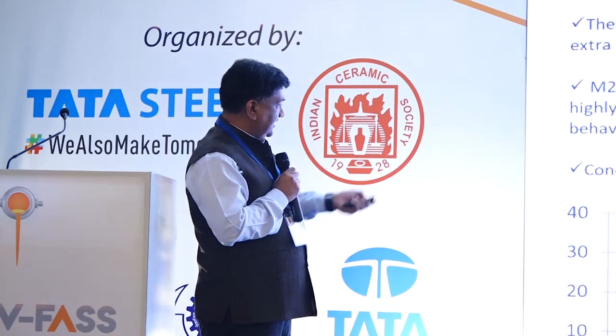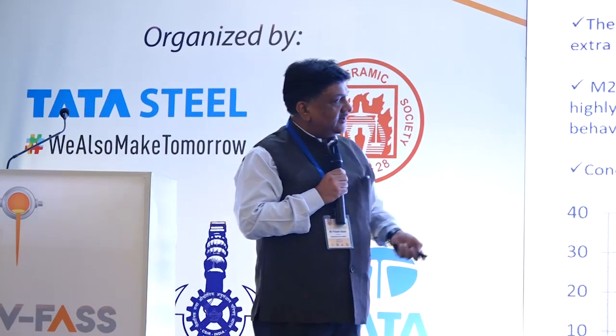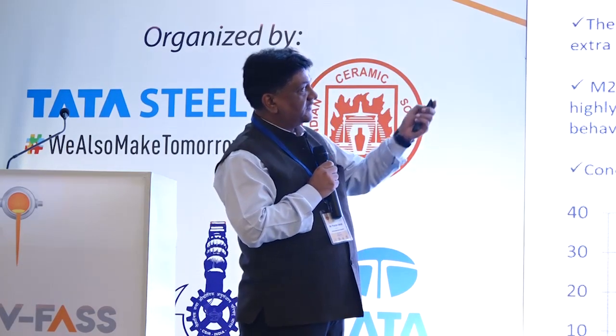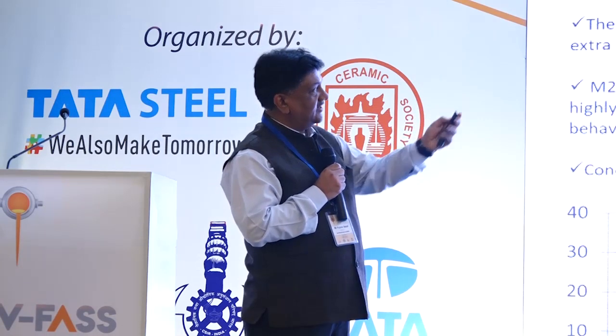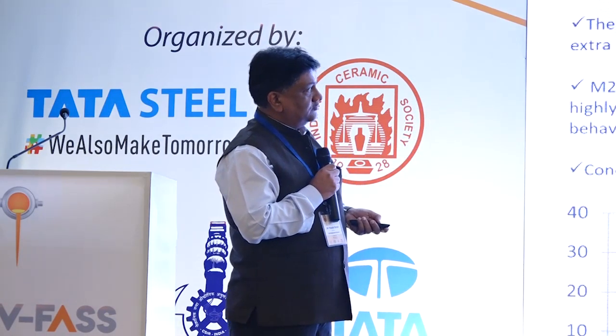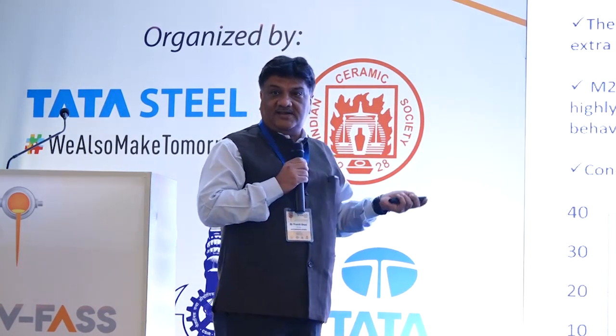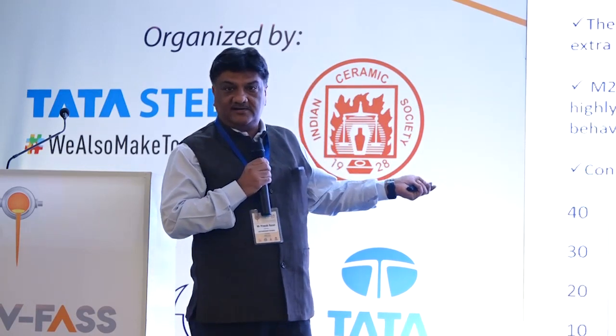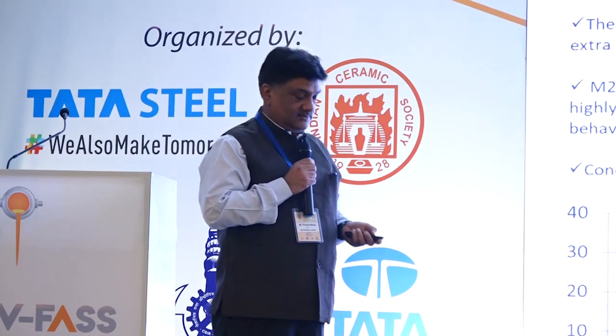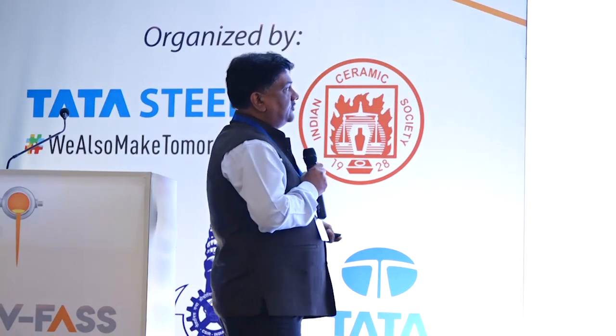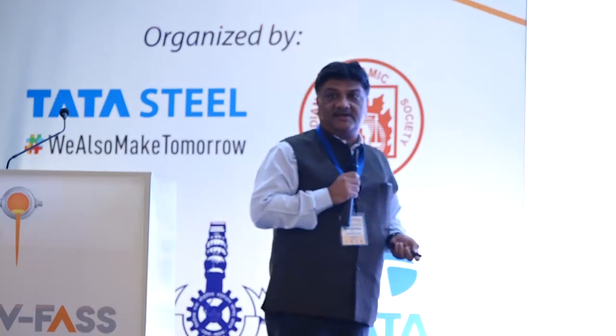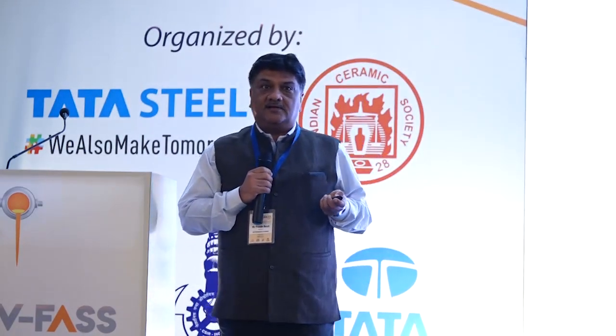And with the strength behavior, you can see with the replacement of 25% of fly ash, the 28 days strength is much higher, 35 MPa, which has been tabulated over here also in both trial mixes, trial mix 1 and trial mix 2. So that's how we made an attempt at the ready-mix Jamshedpur plant for utilization of fly ash. That's been a continuous effort by us.